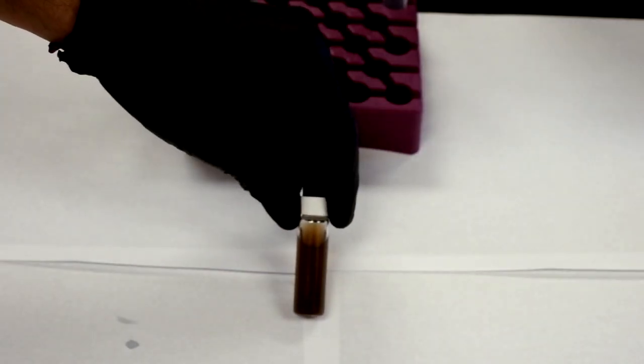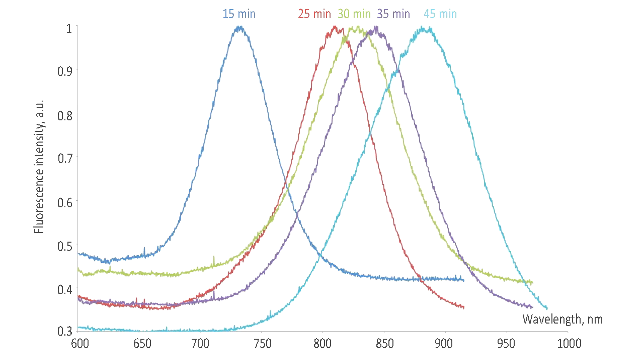This is your zinc telluride cadmium selenide. As the shell has grown, we can see the emission peak shift from about 700 nm to about 850, which is where we usually stop it. This correlates to a shell of about 2 nm.